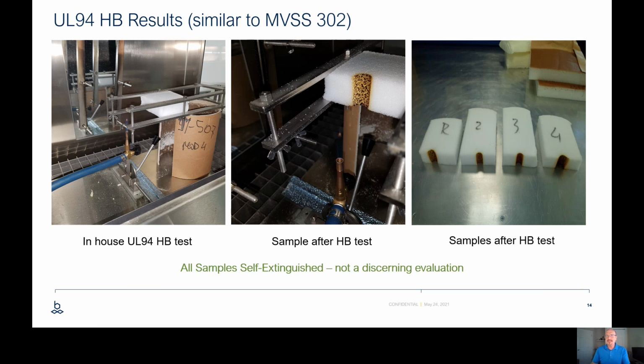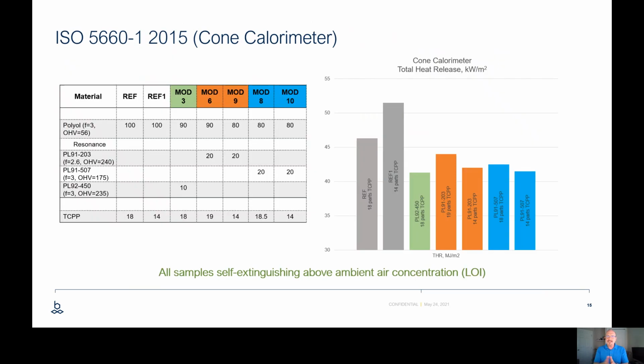We struggled at cutting thin enough foams. For example, the MVSS test is supposed to be 13 millimeters thick, and you can see ours were pretty thick samples, so a useless test, as we found out. All right, so that's our dirty laundry, so to speak.